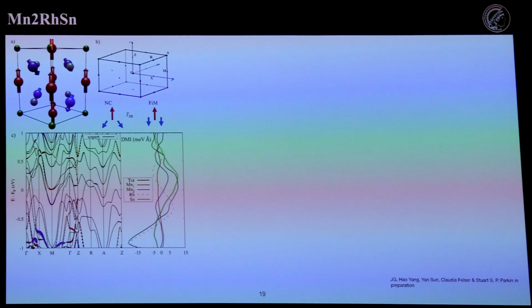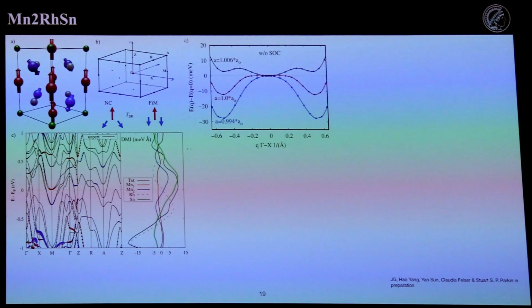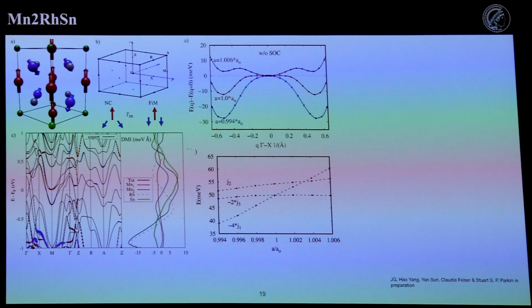So now let's switch a little bit over. Mn2RhSn is actually something very nice because there's a lot of experiments done on it. And so what we did was something not so interesting. We just changed the size of the lattice, yeah? So we put pressure, or we put strain. And what we saw was that this energy dispersion went from having 2 minima to 1 minimum. And what is the reason for this? What you see is exactly that these neighboring exchanges actually changed in their order of who's stronger and who's weaker. This red one is the largest interaction, but it causes everything to be ferromagnetic. The black is the third nearest neighbor interaction, which causes non-coplanar canting.